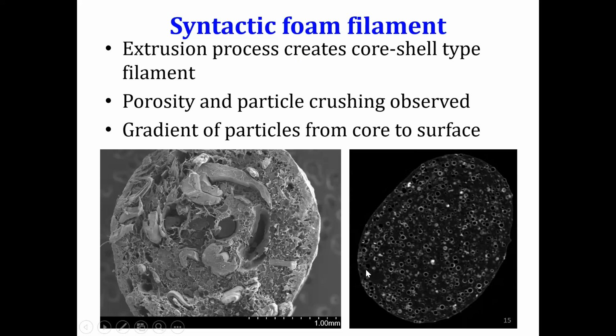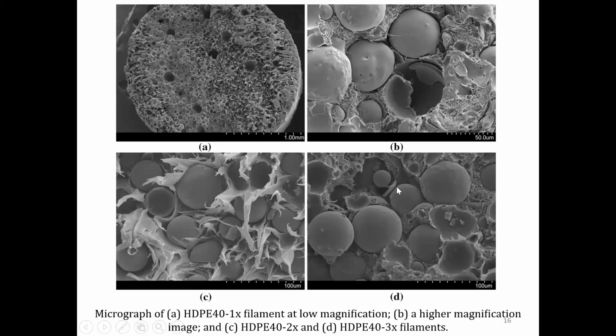We did micro CT as well. So you can see the filament is not spherical, it is in oval form. That is what I was talking about, tweaking the filament extrusion parameters. Over a period of time, we got the grip of the parameters, and then we were able to get a circular filament.